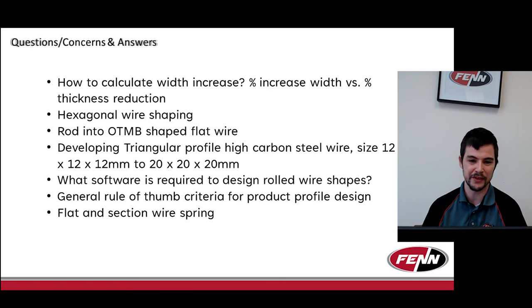And that's the other side of your width spread that I just talked about. Other than your thickness reduction and your roll diameter having to factor, your material has a huge factor. If you're running high tensile spring steel, you're going to see a lot more natural elongation than spread to the side. It will spread to the side in round form, but if I took the same reduction schedule and the same size roll on high tensile spring steel versus soft annealed copper, I'm probably going to get 30 to 40% more increase to the side on the copper than on the spring steel.